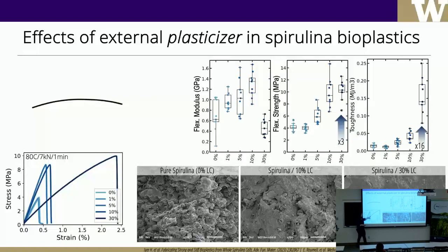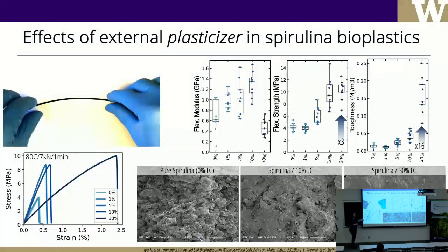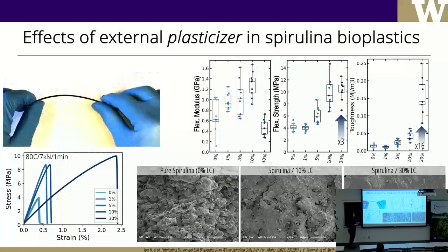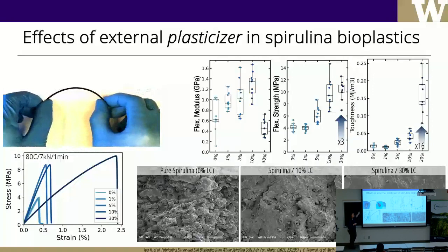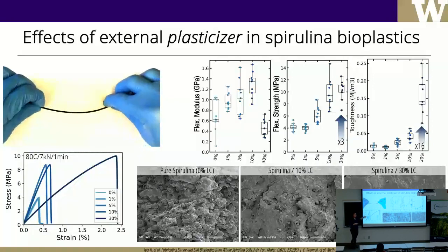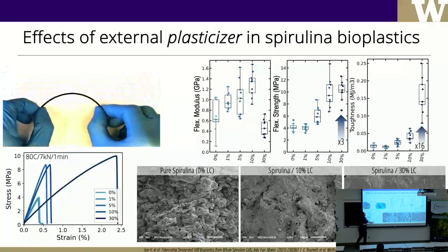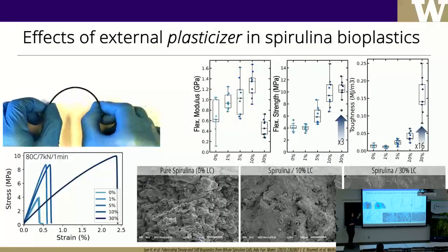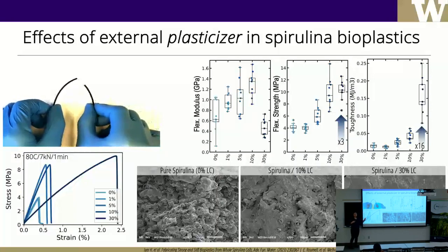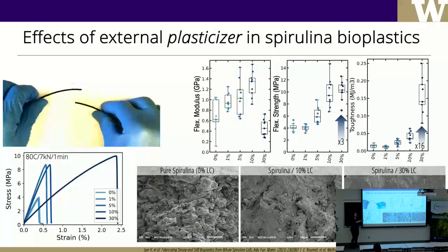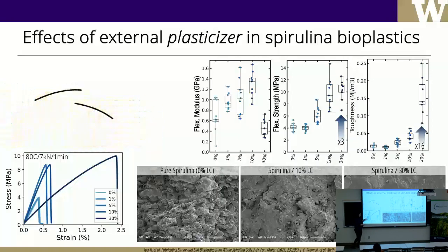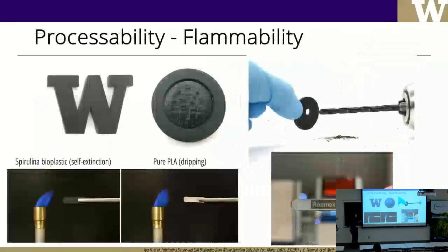And you can see that at the highest concentration, we are able to, at the expense of stiffness, not really strength, but stiffness, have some flexibility. And just for us to understand what 2.5% means, because I don't know if you can tell what 2.5% means, this is a filament that is extruded out of our extruder with a 30% spirulina, so that we can see that indeed this is no longer brittle. If you were to see the one without any filler, you would not be able to do anything. At 0.5%, it's gone. So you can play with that.